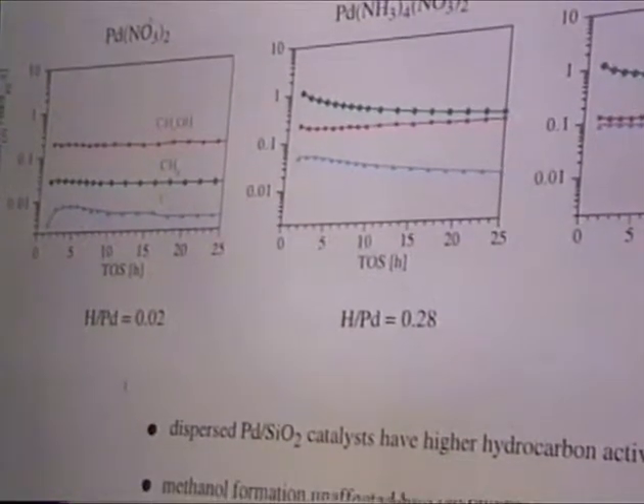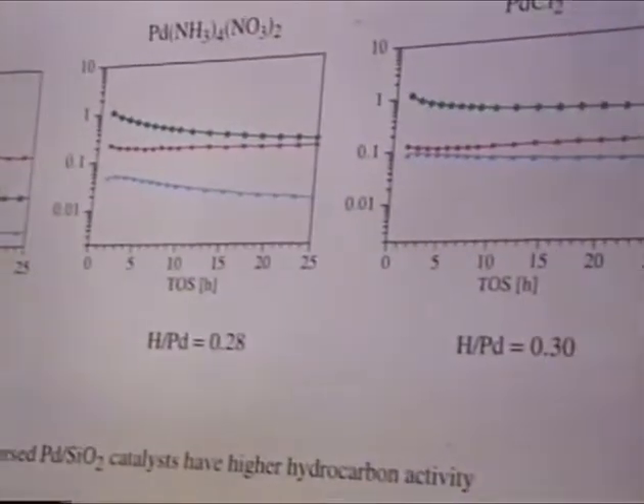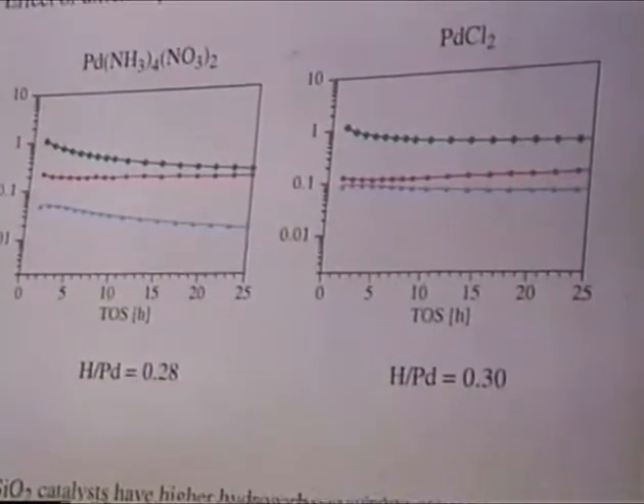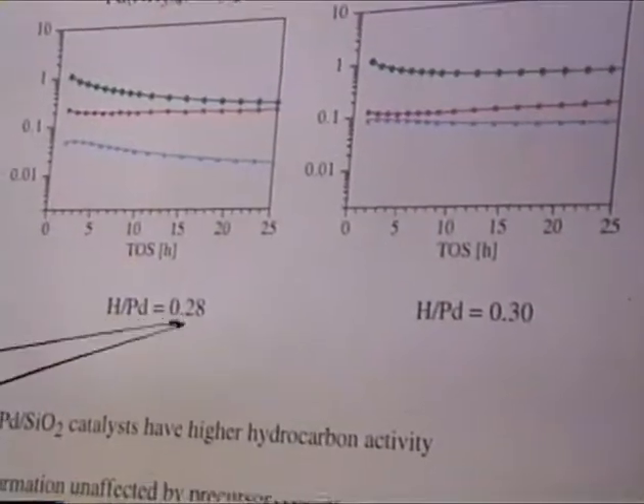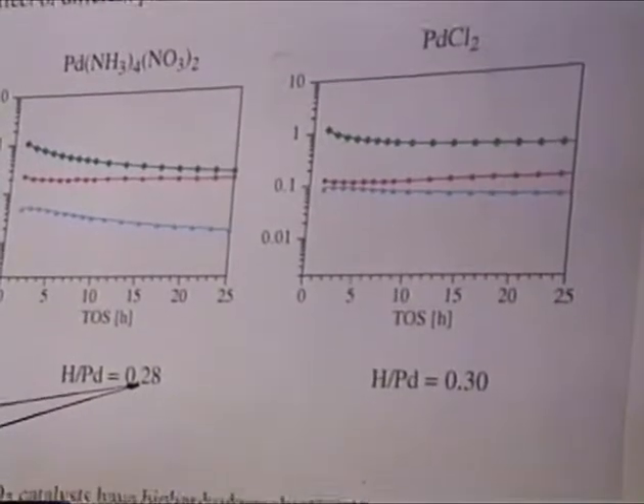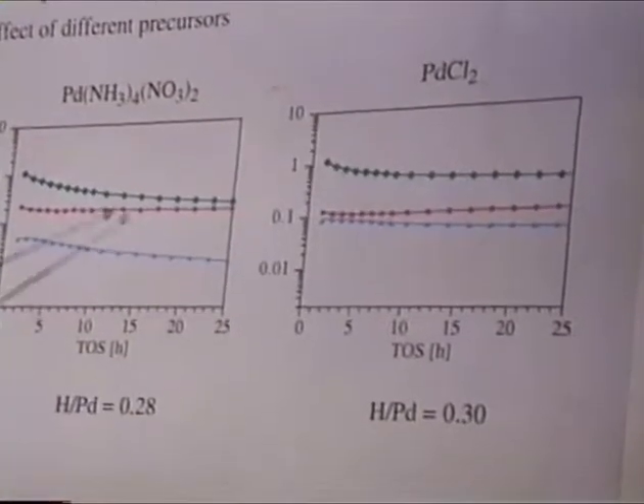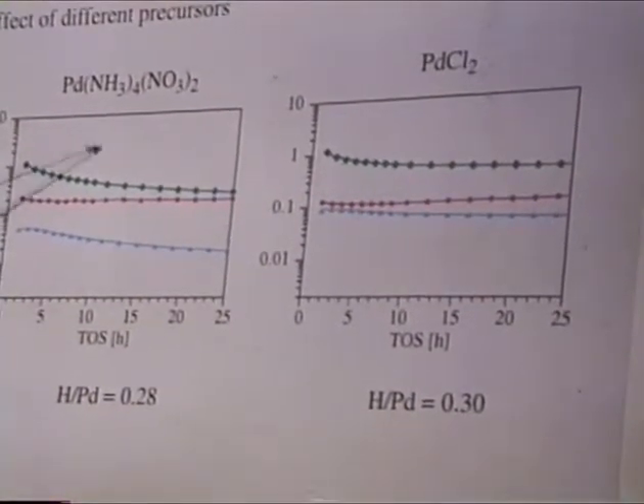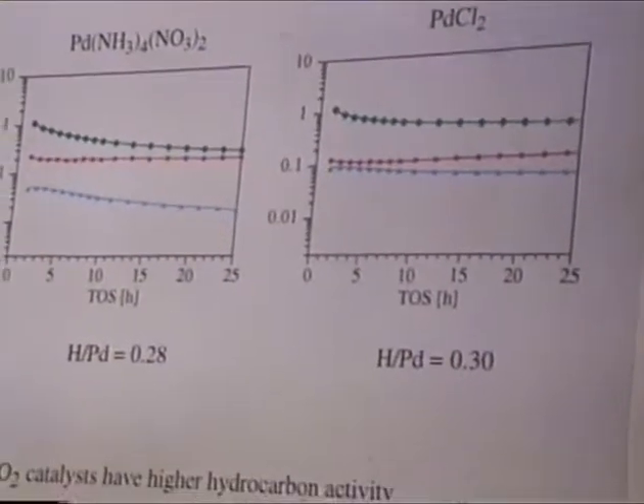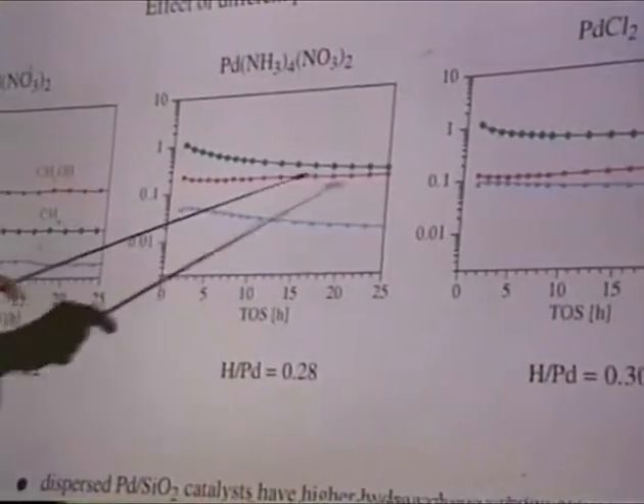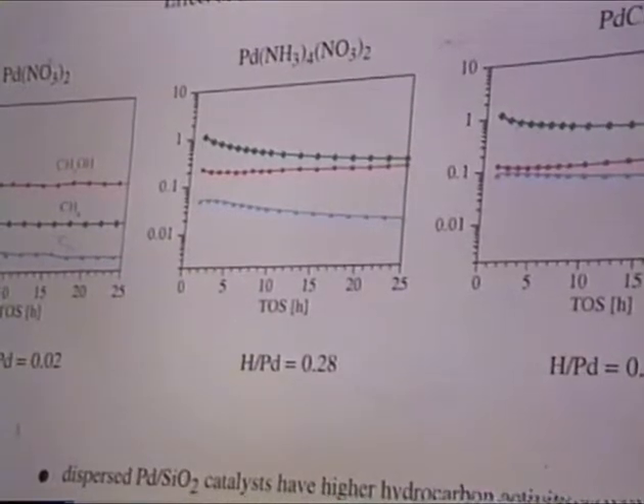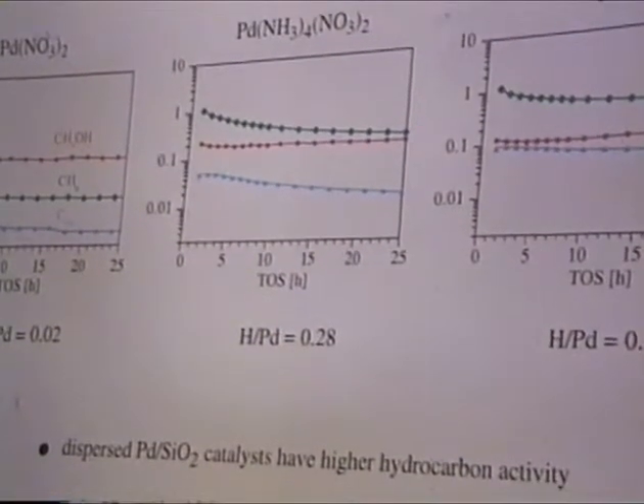Only when you go to very small particles, or you go to kink sites on a single crystal, then you can dissociate CO. And that's why on the much higher dispersed palladium, you can dissociate the CO, and you make somewhat more methane and C2+. Look at the methanol, it's equal, and it's very low. So still, it doesn't matter actually which salt you take.